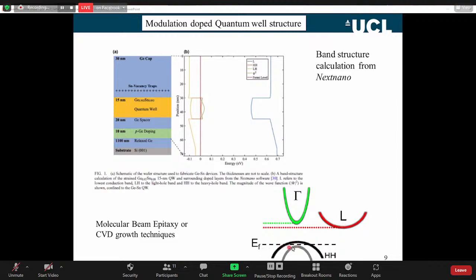You can see what's happening in the valence band. This is the chemical potential here. We just have this heavy hole band. The light hole band is split off for two reasons. One is quantum confinement, we made a quantum well. The second reason is strain. So that strain shifts the light hole band away from the heavy hole.